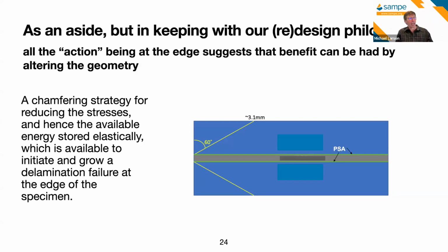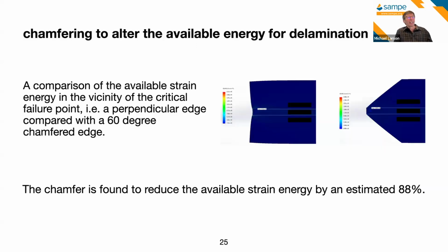So what about a simple chamfering strategy of just chamfering the two layers, top and bottom? What does that do with changing the material? And a simple finite element model of looking at a chamfered surface, and not, with that same delta T being applied. In this particular case, it was like a 90% decrease in the amount of strain energy in that sensitive domain of intense shear to be available for delamination, and the energy needed to take the adhesive apart.